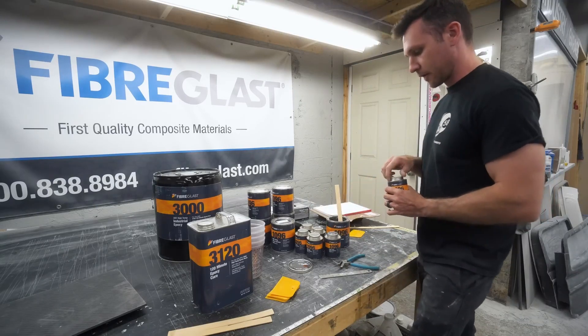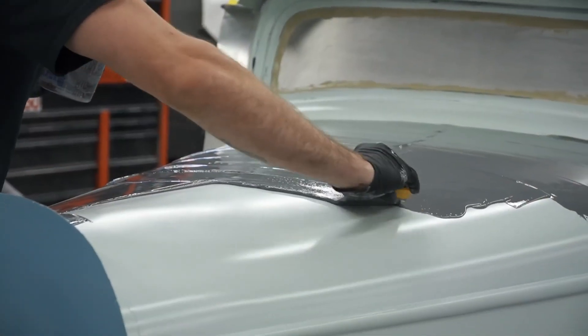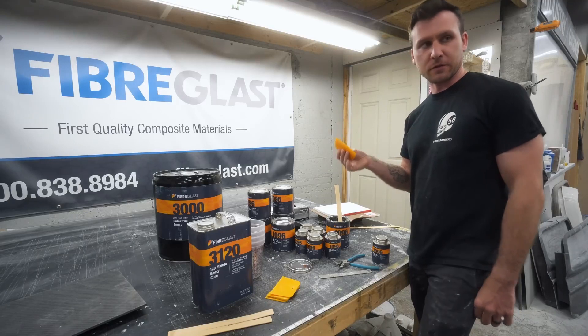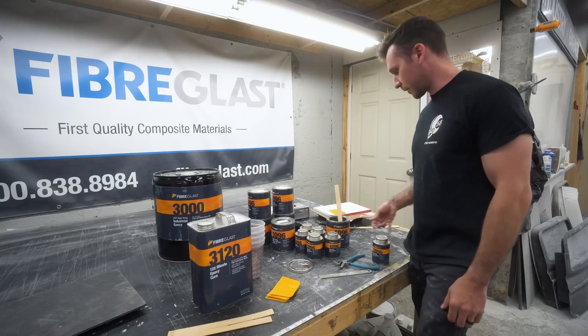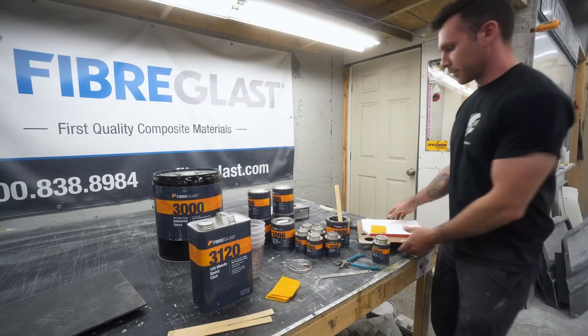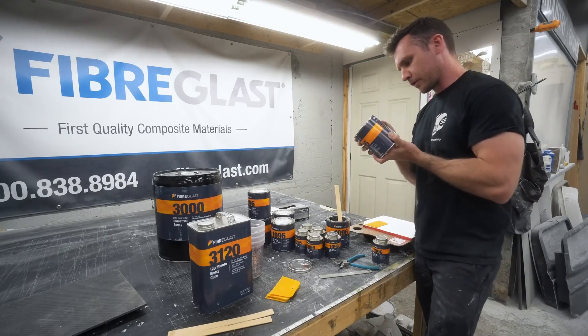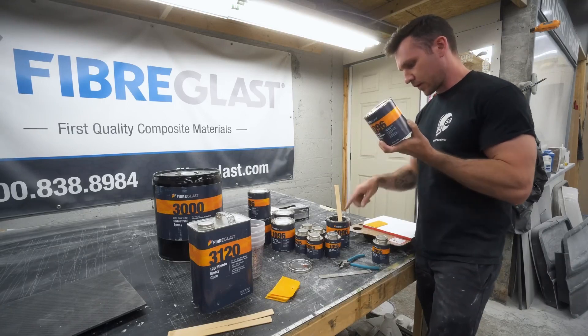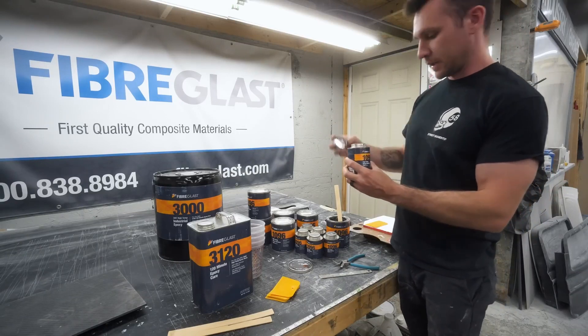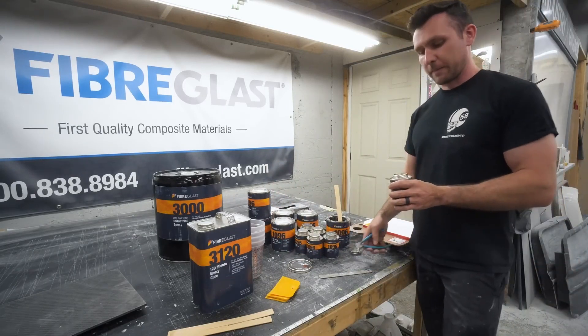You want to start by measuring out your 1096. I've been told you can use a brush or a spreader, and it's similar to a thin body filler. I might use the spreader because that's natural to me from all my years doing bodywork here at the shop. You mix it at 100 parts Part A to 12 parts Part B, which is the hardener.